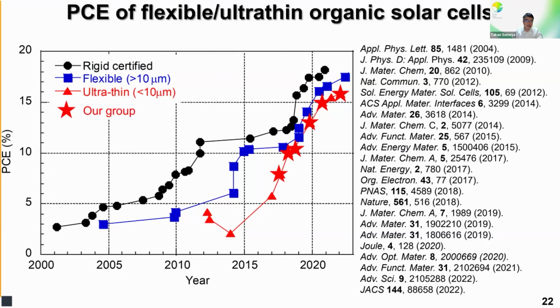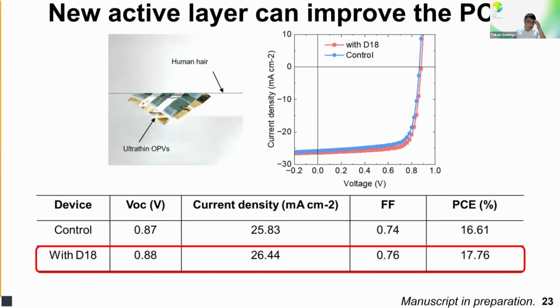Because the ultra-thin film easily gets damaged by plasma processes, like high energy processes. Thereby, we need to reduce the use of high energy processes. And another difficulty comes from the process temperature. Ultra-thin film is easy to shrink with elevating temperature, so we have to reduce the process temperature, ideally to room temperature. And thanks to recent intensive effort, we can achieve fairly high efficiency on ultra-thin film with a thickness of 1 micron. One of the good values in our group is 17.7%.